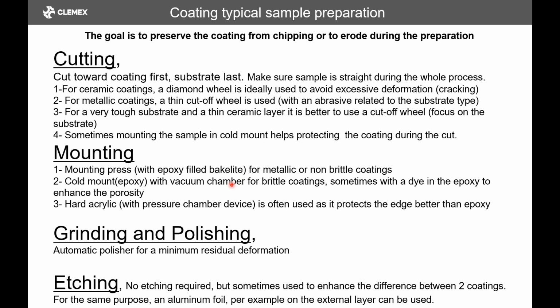In the aerospace industry, I've seen a lot of people using hard acrylic with a pressure device instead of a vacuum chamber. Basically, it's a 3-part acrylic, and it's quite hard. It's harder than epoxy. The way it works is that you put that into the chamber, and it's a positive pressure, so it's applying the acrylic against the coating, and then it protects the edge quite well.